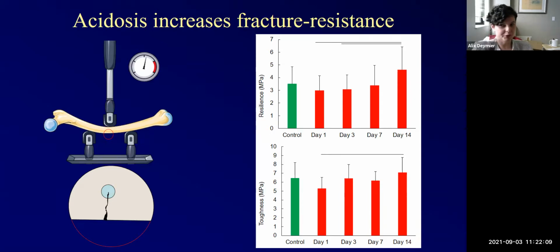We're getting both physiochemical and cellular changes, we're getting changes in composition, and that is going to affect my toughness by arresting cracks through the formation of a plastic zone. Now I am seeing these changes that are probably cellular. You're not going to dissolve bone into a new shape. That seems to really be a cellular behavior.